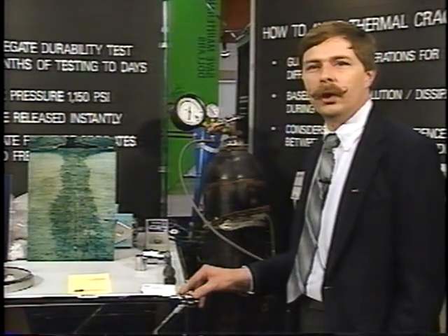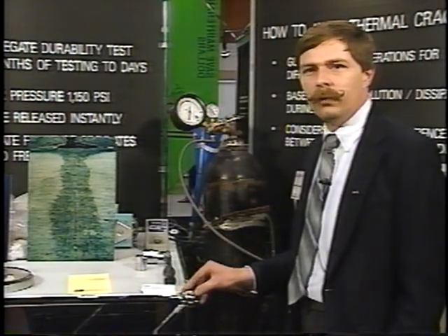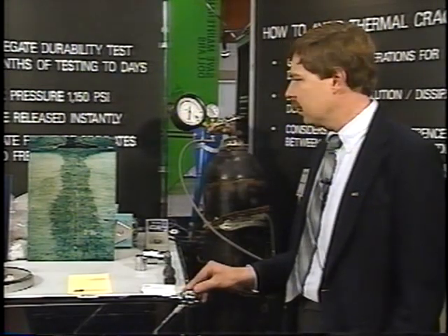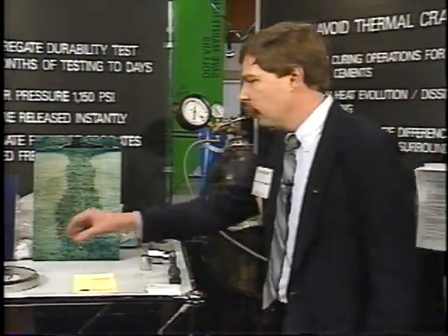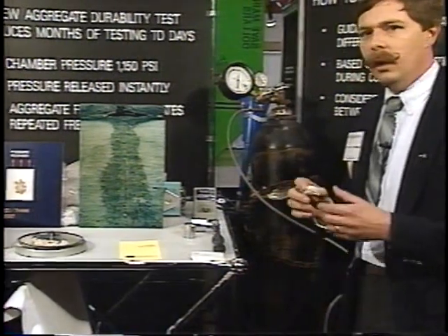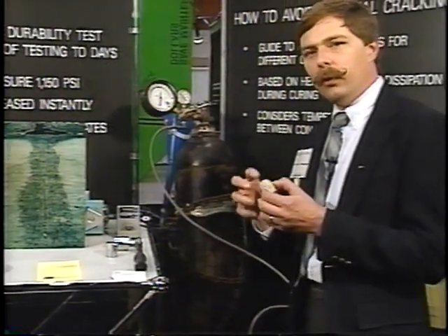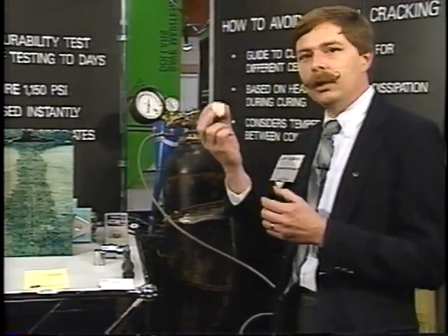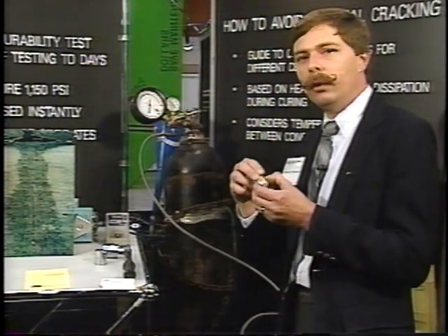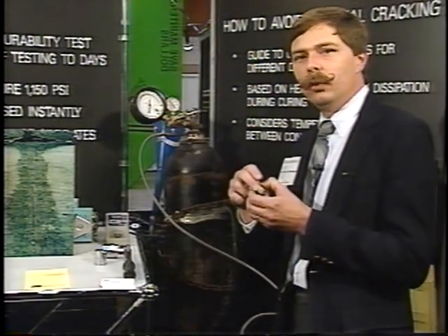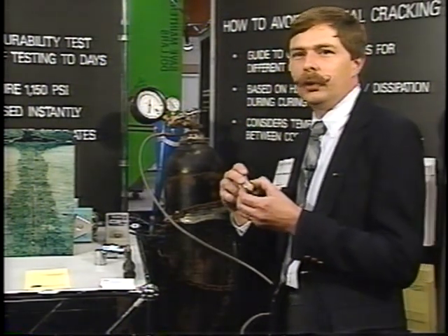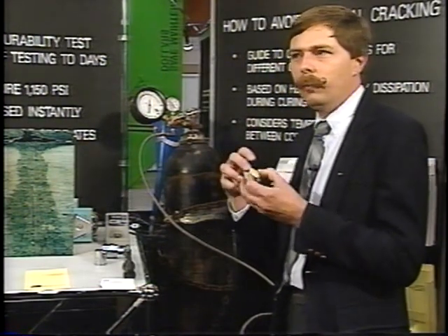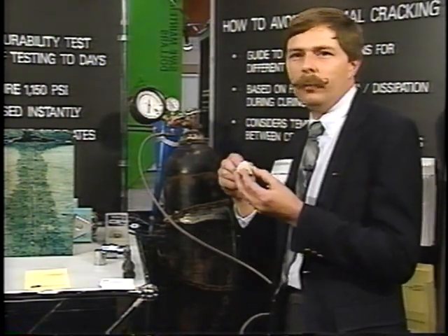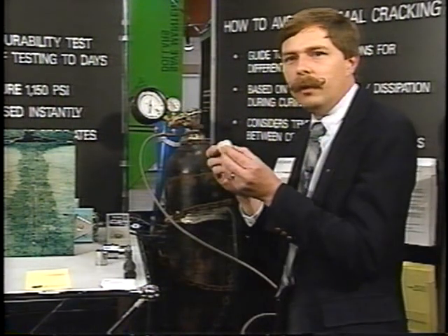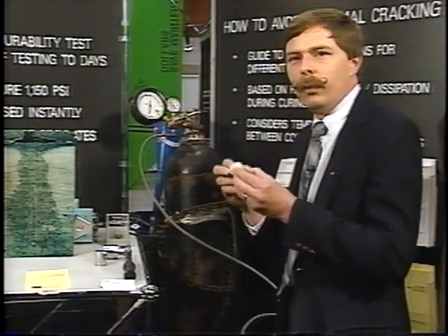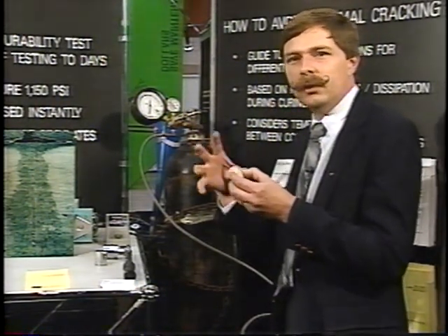What we did in the SHRP freeze-thaw project was to develop a more rapid test. Instead of making concrete beams, we take the aggregate piece and surround it with water. It starts out oven dry, we surround it with water, and we pressurize it to 1150 psi pressure. This forces water into the pores, compresses the air in the pores, so we have pressure on the outside and pressure on the inside. We then rapidly release this outside pressure.